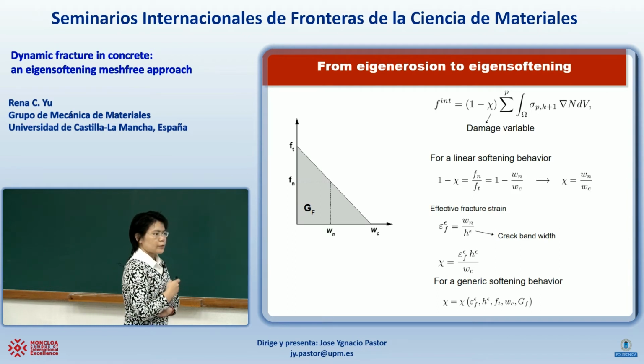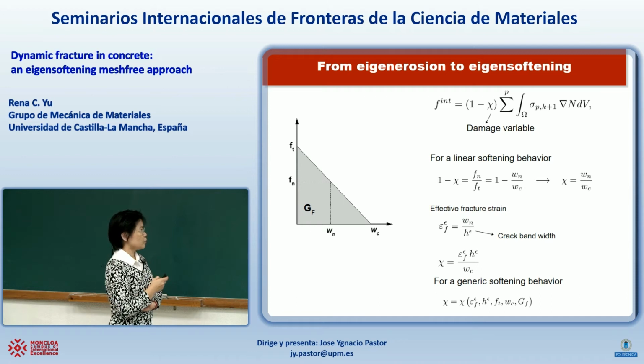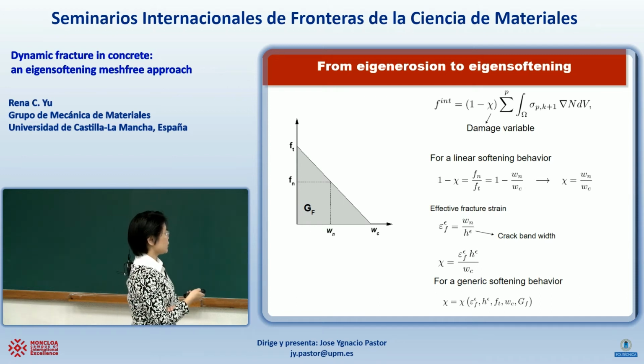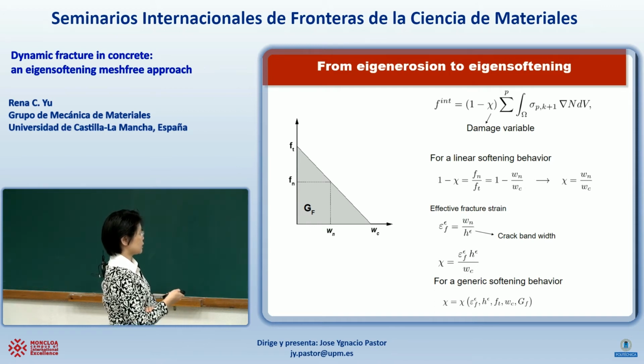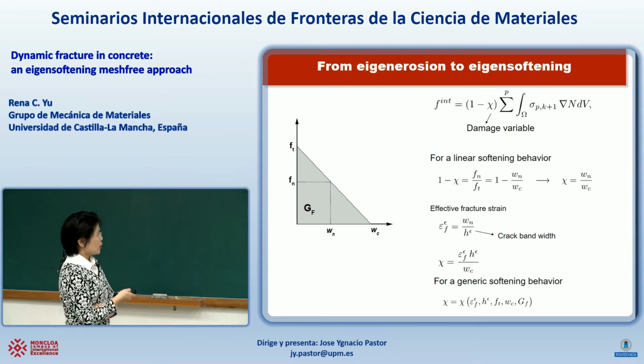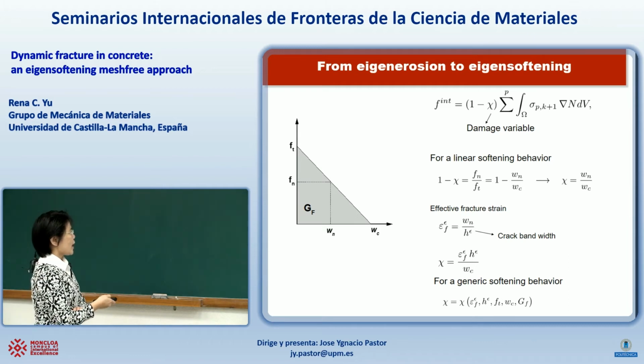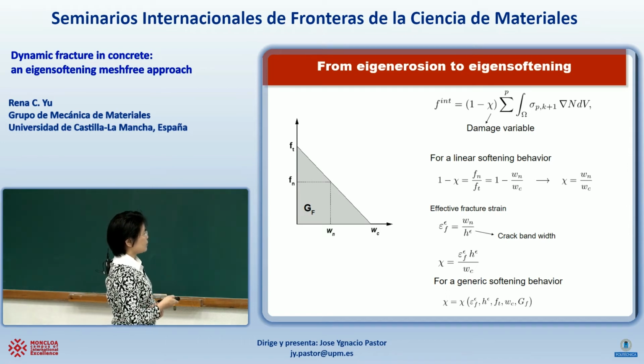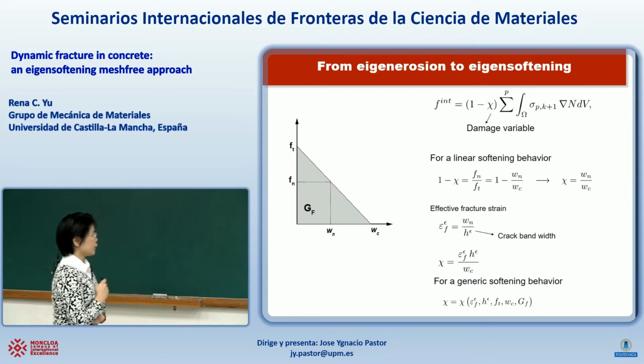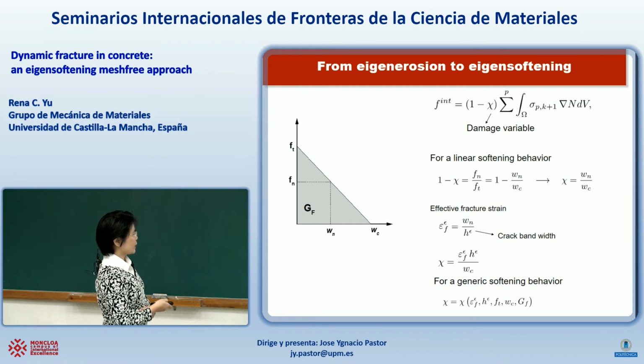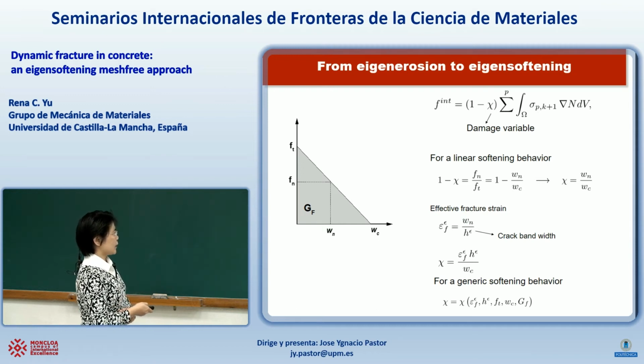Since we're using material points which represent a volume, we don't really have an opening. So we define our effective fracture strain. Actually, this was a term used by Bazant. So this is our opening Wn divided by a length, which is called the critical bandwidth. In concrete this is like 2 to 4 times the maximum aggregate size. And then we have the damage variable defined as the fracture strain times this bandwidth divided by the critical opening. So if we use a general type of softening behavior, we need to define the damage variable as a function of the fracture strain and the bandwidth, and also the tensile strength, critical opening, and fracture energy.